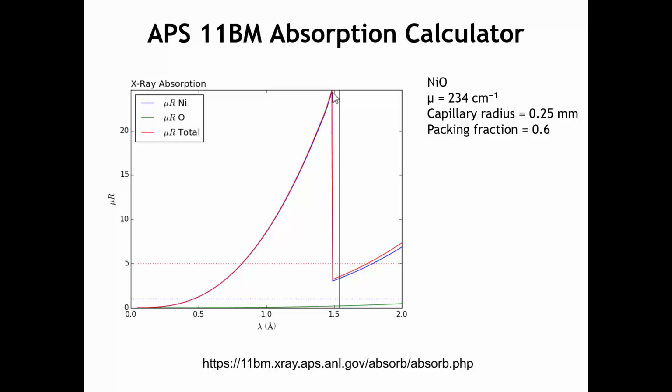It can be used, let's say, to accentuate the difference in scattering power of two elements that are close together on the periodic table. And at any rate, it is something that you have to think about when you're doing refinements. When you get close to an absorption edge, the scattering power of your element actually goes down.